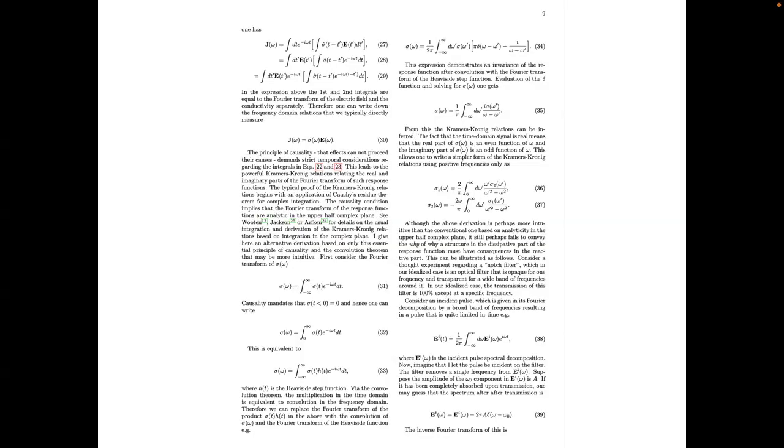Complex quantities are essential. One advantage of optical responses is that there's a correspondence between what can be measured in experiments like terahertz spectroscopy, when you look at magnetic systems, where we can measure the magnetic susceptibility, and things measured in neutron scattering. When doing experiments with the optical conductivity, unfortunately, we can only measure at zero momentum. But the advantage, over neutron scattering, is that you get the real and the imaginary parts at the same time, and that can be very useful for analysis. Okay, so complex responses are something we're going to make lots of use of.